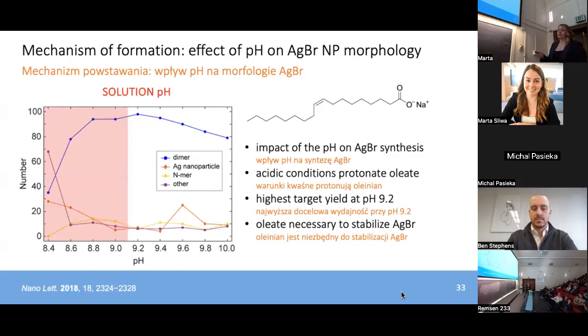So we see that drop in the number that we count, and a higher number of byproducts like clusters of silver nanoparticles, silver bromide multimers, and dendrites that are super susceptible to reduction when we look at them in the microscope. So we posit that at these acidic conditions, the sodium oleate, which is stabilizing that silver bromide host, is protonated at that carboxylate moiety, which it uses to interact with the surface of the silver bromide nanoparticle. When you put a proton there, it can't interact with that surface and therefore effectively stabilize those host morphologies.